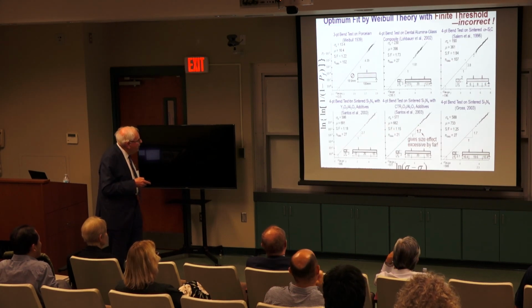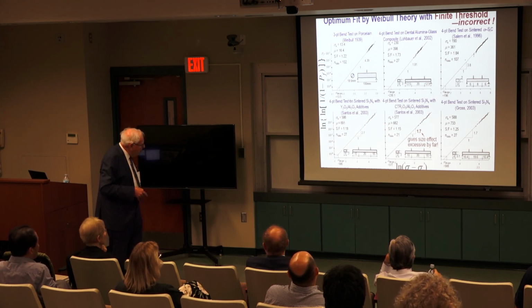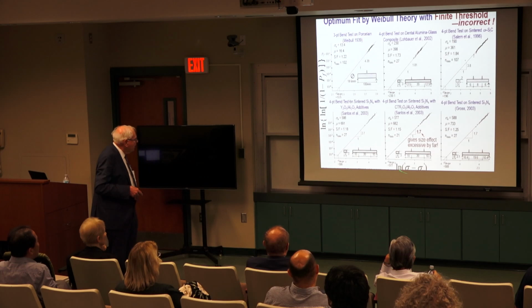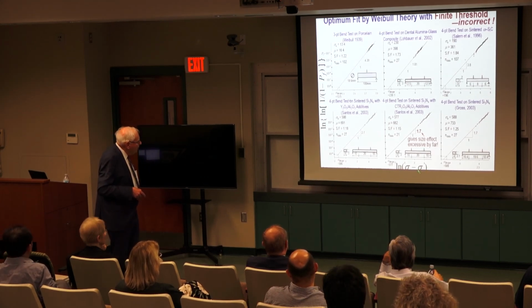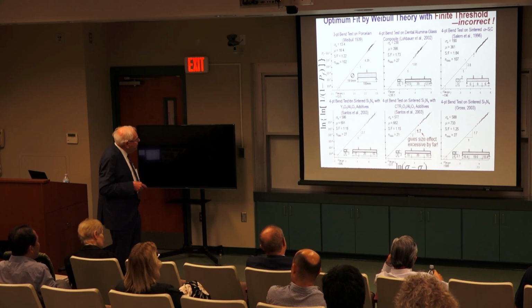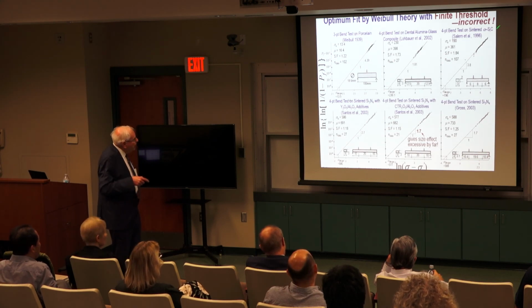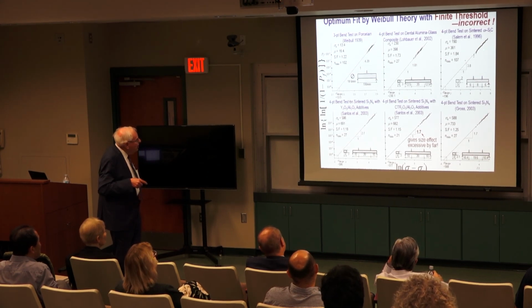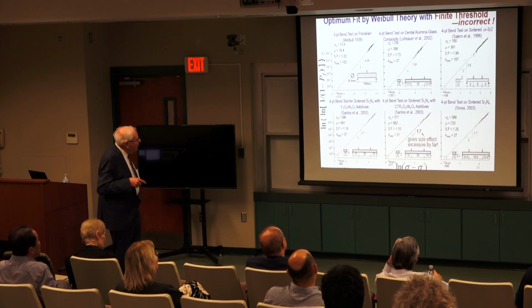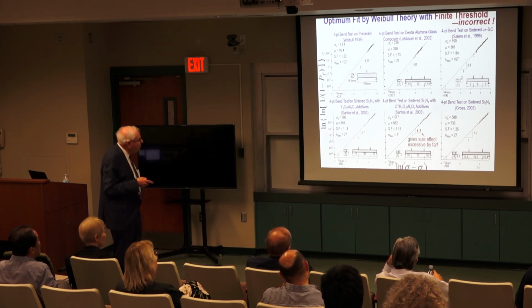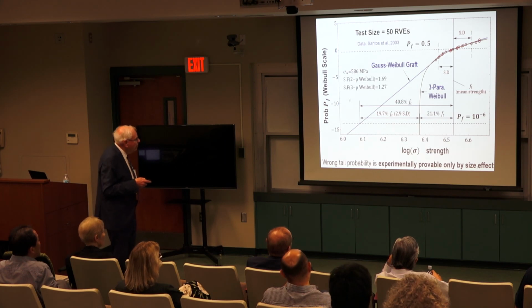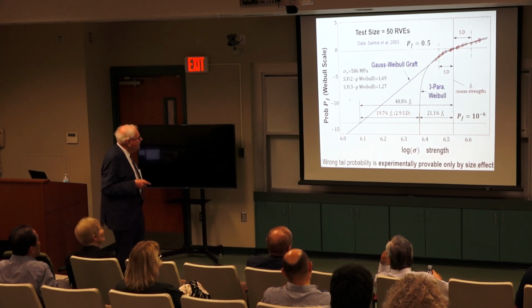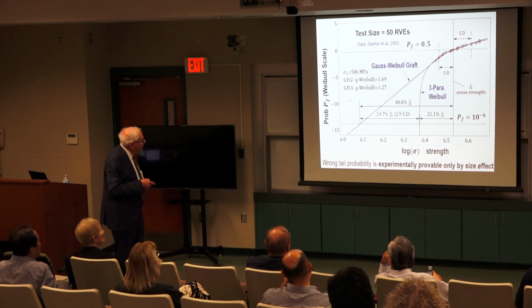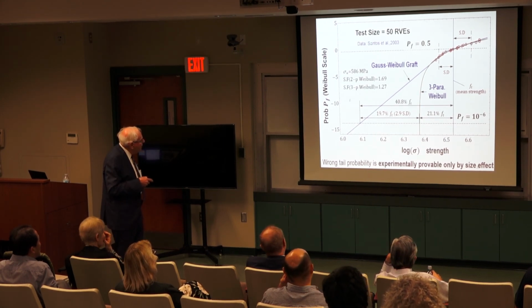But what they do, they fit it by a distribution with a threshold. I'm sorry, this somehow is cutting the bottom of every slide. I don't know. There is sigma u, the threshold, here. Now, if they plot it in that scale, they also get straight lines. But you see how compressed these diagrams are. The coefficient of variation is actually higher. But they are in principle incorrect. That can be seen if you consider extensions and if you consider the size effect. So in Weibull scale, I take this data from this picture by Santos.